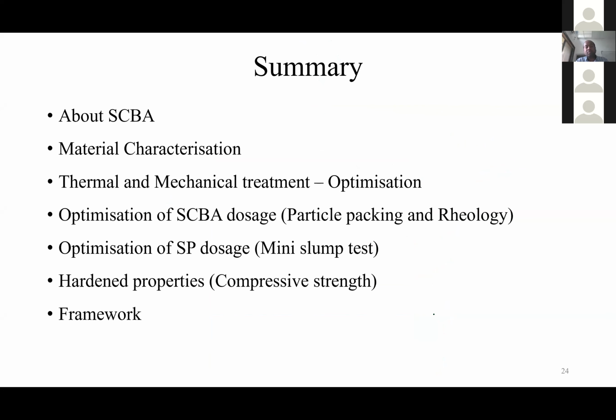The summary of what we have discussed. We have discussed sugarcane bagasse ash, its material characterization, and thermal and mechanical treatments, how to optimize and rationalize it, and what the important points are under thermal and mechanical treatment. Then we have discussed two concepts, particle packing and rheology, following which how to optimize SP dosage and validate through compressive strength. Based on these things, we have proposed a framework. Based on the framework, there is clear evidence that we can maximize the potential of SCBA usage in cement concrete.